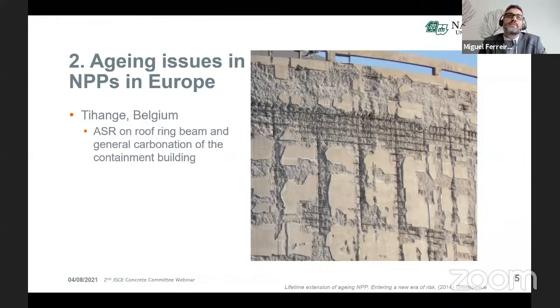However, what makes the aging different in the case of nuclear power plants is the uniqueness of the structures themselves. The containment building, for example, is a structure 1 meter thick or more, and it's very heavily reinforced, more than conventional structures, with pre-stressing tendons, sometimes in both horizontal and vertical directions, and it can have a steel liner embedded or on the surface. And sometimes there's even a double containment. So this makes the typologies that we are dealing with quite unique, and we don't have experience with those kinds of typologies and aging mechanisms.